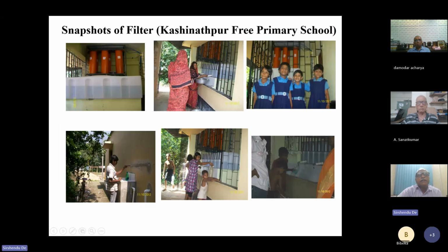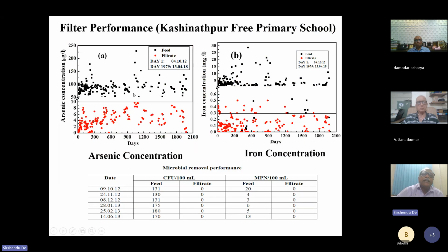This is the performance of these filters. This data is for 6 years, from 2012 to 2018. In the left panel we have put the arsenic concentration, and in the right panel the iron concentration. For arsenic, the black dots are the concentration in the feed and the red dots are the concentration in the filtrate. The black dots vary from 50 to 225 or 230 microgram per liter at certain times. There is a seasonal fluctuation: during summer, because of lack of rain, the arsenic concentration shoots up. During the rainy season, because of dilution, the concentration goes down. But in the filtered performance, the red dots, the concentration is always below 10 microgram per liter. There is also fluctuation, but it is well within the safety limit.